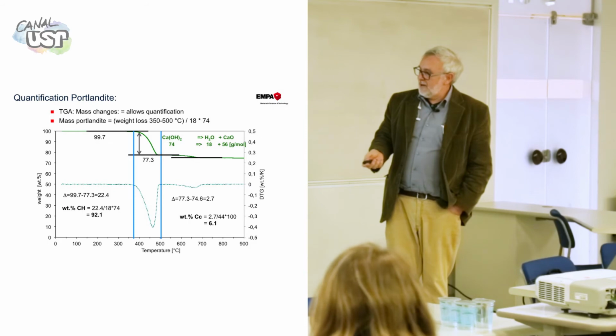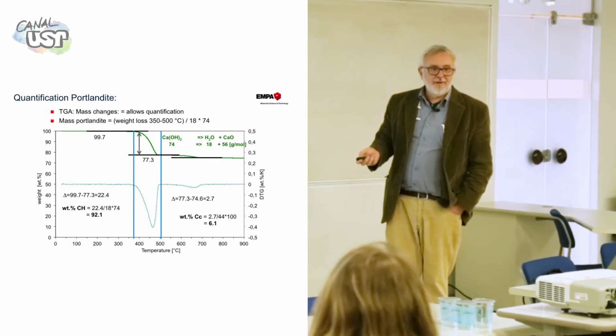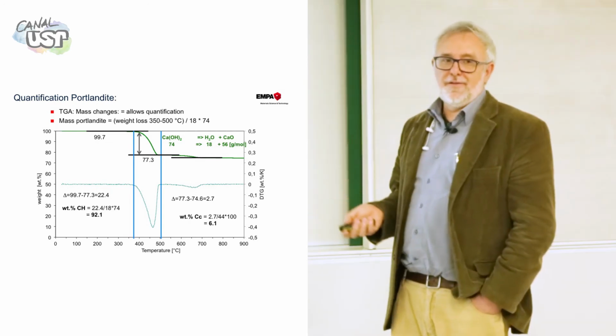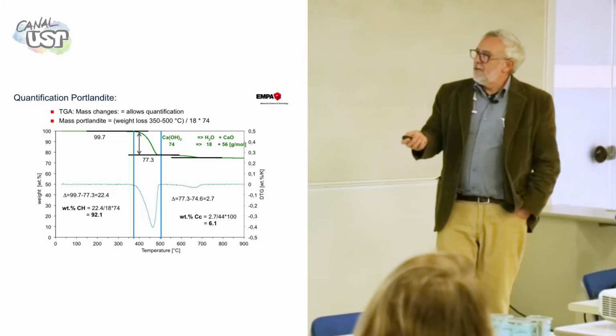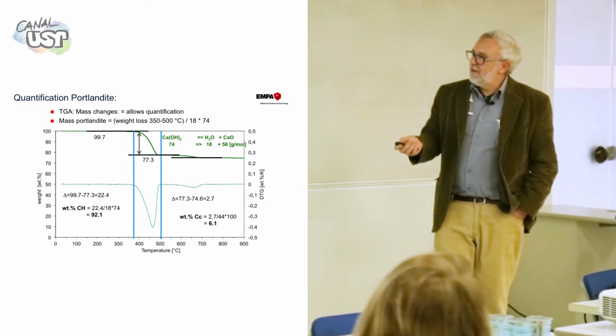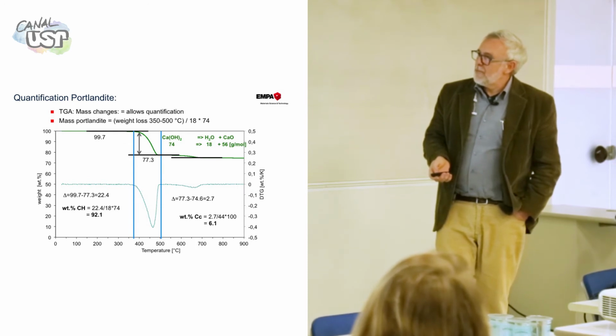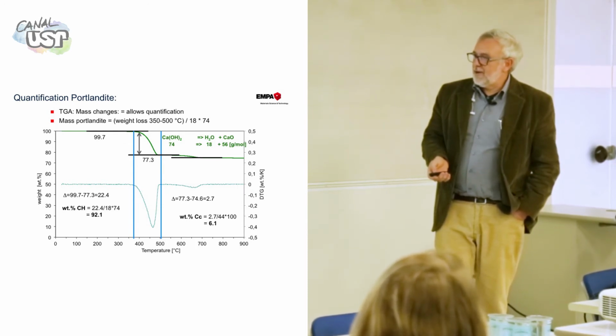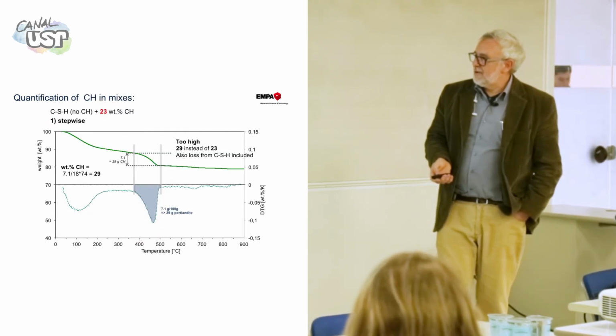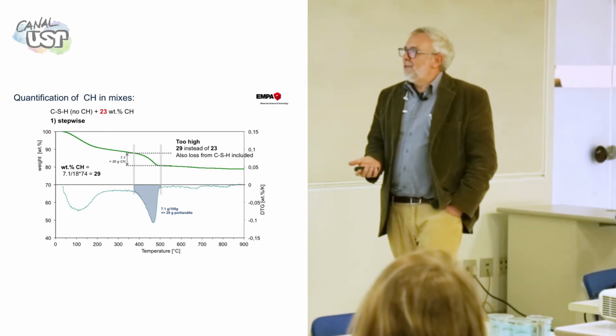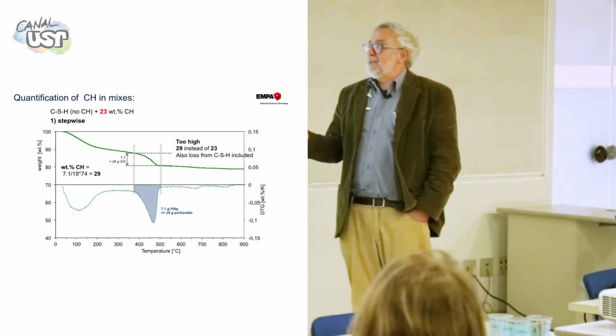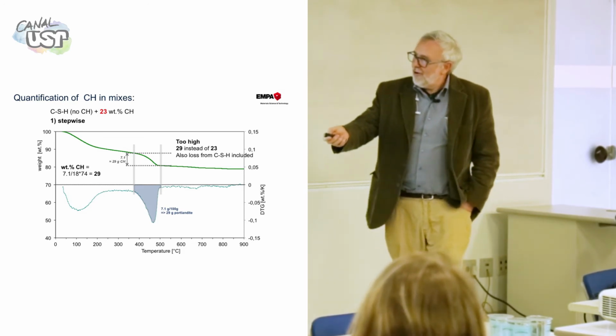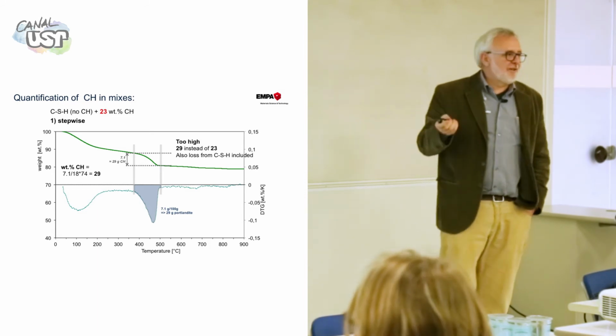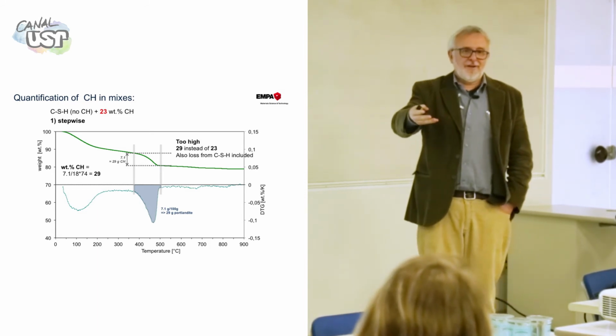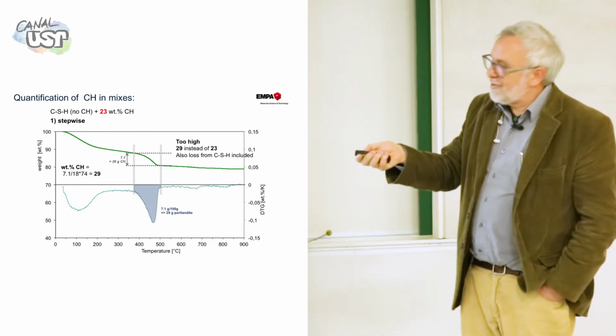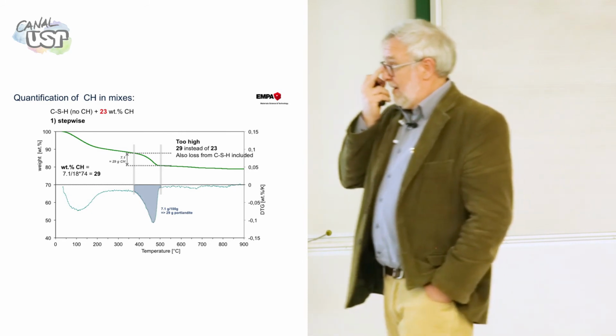And these are the peaks. In this case, it's 450. It's a small sample. If you go to 1 gram, it's going to be 550 because it's a bigger sample. So you have mass here, mass after the peak, then you can calculate it. Okay, it's just stoichiometric estimation. You can see how much it is. But if you have a mixture, a cement, you have CSH losing water all the way to, let's say, 600, 700 degrees. On top of that, you have portlandite decomposition within this range.